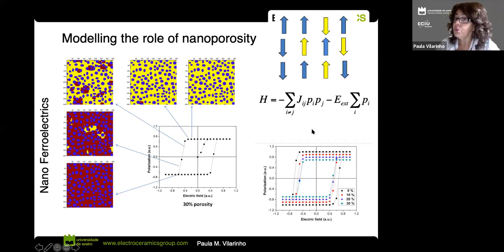This is a theoretical prediction. This was our theoretical result. So what is the reason for this? We were really struggling a little bit, but what we think is that when we have this nanoporosity very well organized, distributed in the lattice, they will really help to create electric field conditions in which the switching is easier. So they will somehow counteract the effect of grain boundaries that are pinning the switching.